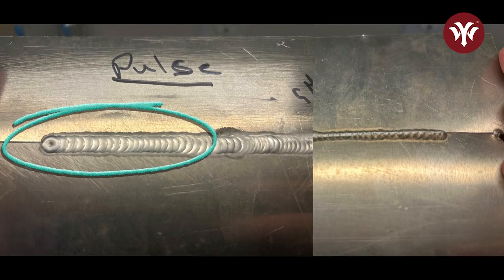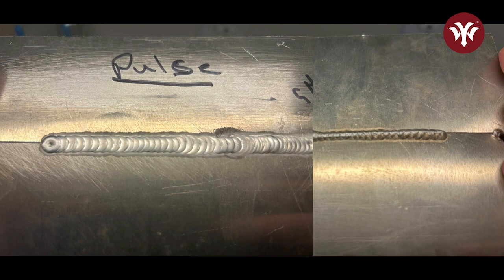When you take a closer look at the coupons here for pulse settings, it really shows how much nicer using pulse can stack up the beads. By allowing you to travel with low current, you tend to not wash out the bead, and you can really stack it up. And when you look over to the backside, I was really impressed with the penetration as well. It seems that ramping up to that weld current really helps to dig in. So I was quite impressed actually using pulse, more than I thought.